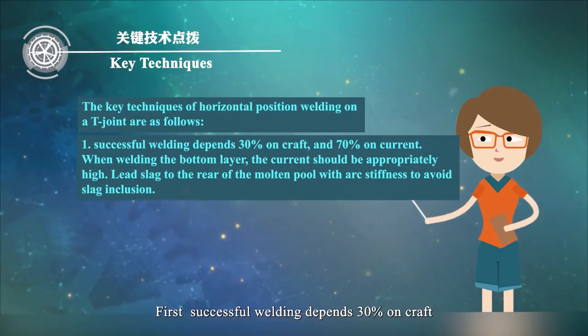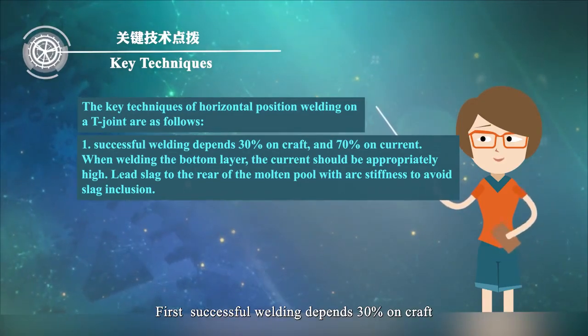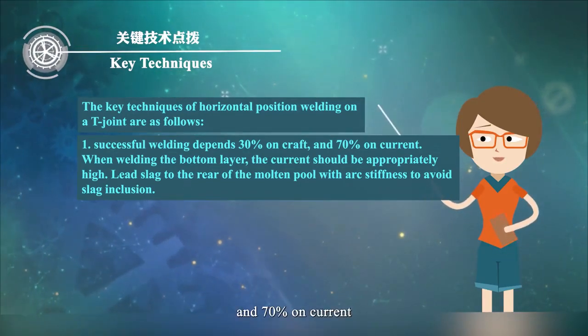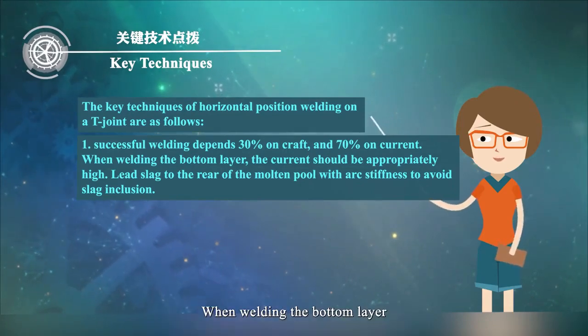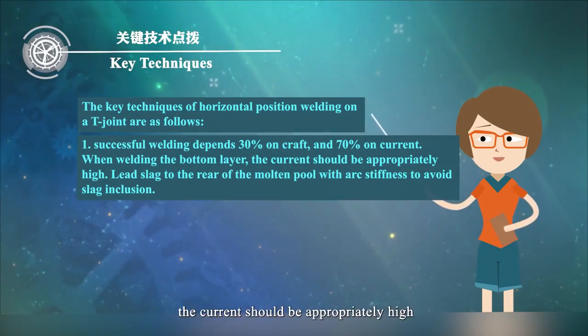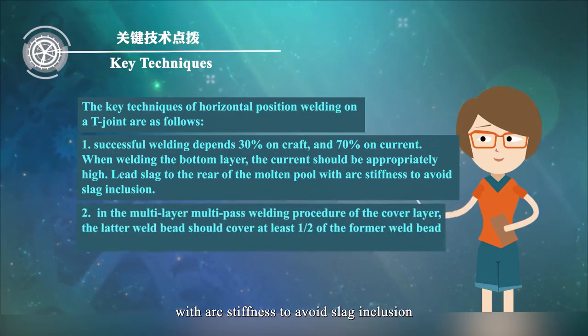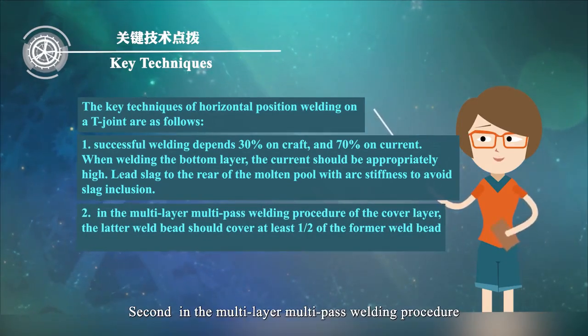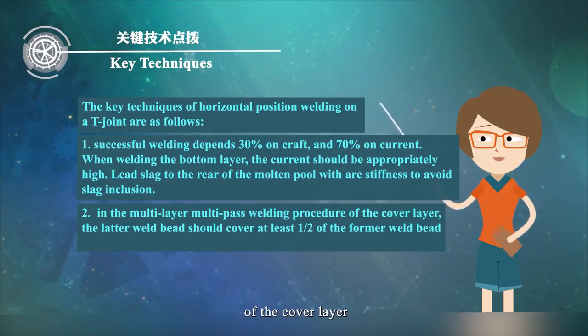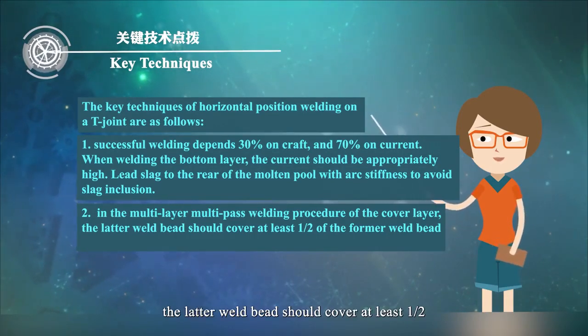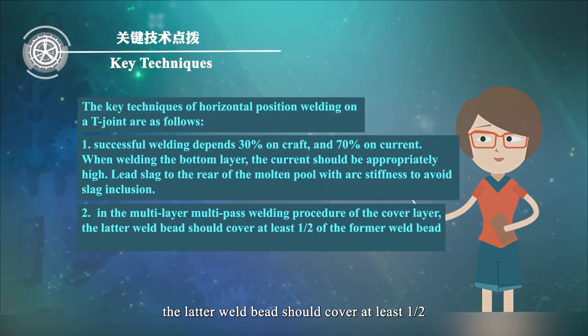First, successful welding depends 30% on craft and 70% on current. When welding the bottom layer, the current should be appropriately high. Lead the slag to the rear of the molten pool with arc stiffness to avoid slag inclusion. Second, in the multi-layer multi-pass welding procedure of the cover layer, the next weld bead should cover at least 1/2 of the former weld bead to ensure neat formation of the weld bead.